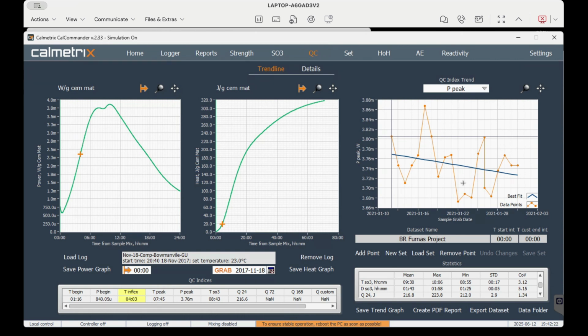It's just from the scale that's here, it looks dramatic, but in reality, it's quite nicely maintained, and you can see it here in the coefficients of variation that are like 3.12% for the time of SO3. That's really good. For the power of the peak, within 1.31%, that's really tightly controlled.